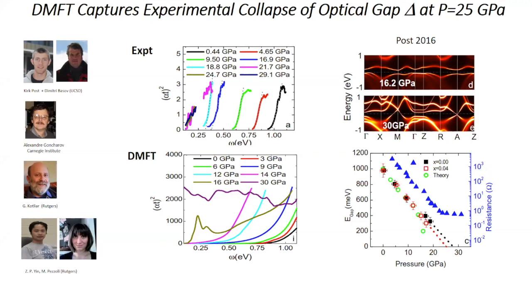And you can see that as you increase the pressure and go towards the left, I wonder if you can see my little arrow? Yes. All right. And so this is increasing the pressure, and you see that the gap, which is where this line intersects the axis, it's about 1 eV at low pressure. And it moves to lower values as we increase the pressure. And somewhere between the cyan data, which is 19 GPa, and the pink data, which is 22 GPa, you can see that the gap disappears.